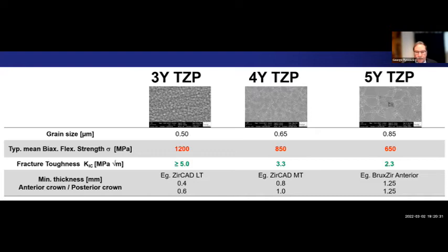Try to remember what we talked about before: we said Emax had about 500 to 600 biaxial flexural strength. If you look here, the traditional zirconias, the 3Y, have up to 1200 megapascals of flexural strength. So that's more than double the strength of an Emax restoration. When we move to the 4Y, as we try to get more translucency in this material, the 4Y materials drop to about 850. And then some of the purest zirconias from an aesthetic standpoint are at 650, so very comparable to a lithium disilicate.